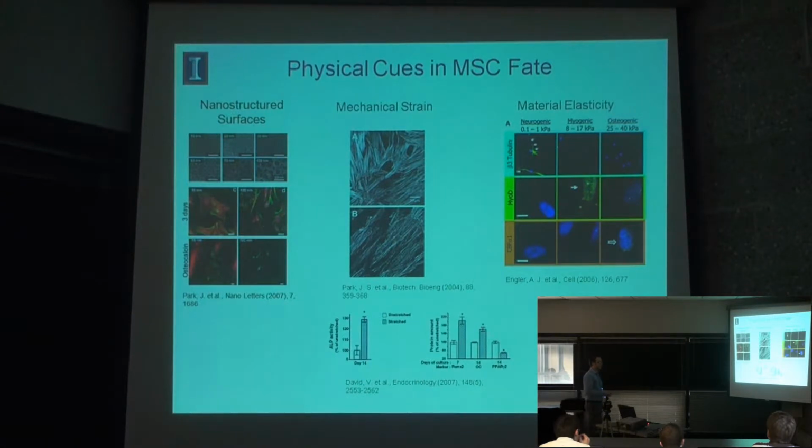And what they did is they did a simple experiment by varying the stiffness of polyacrylamide gels, so standard gels used for running protein gels, from very soft gels that approximated the stiffness of brain tissue, so less than 1 kilopascal. And then they increased the cross-linking density of those gels to make them more rigid, to approximate that of muscle tissue and bone tissue.